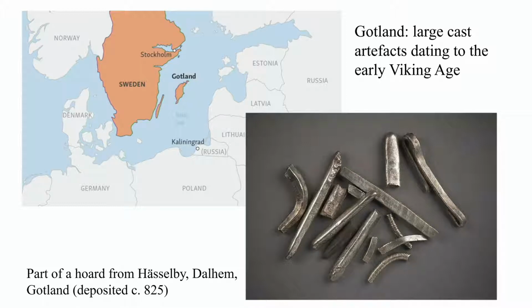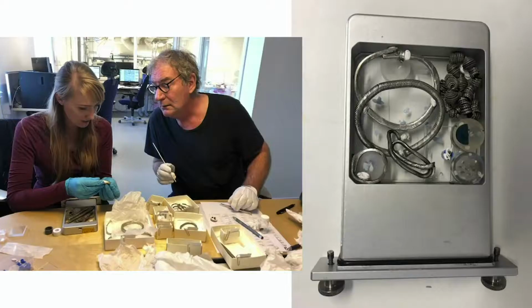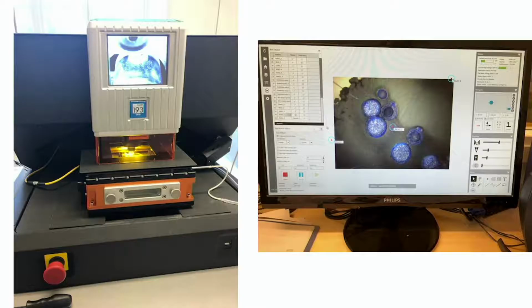And here is an example of a hoard that we also looked at. Here it had some coins with it, but most of the silver is, as you see, as rings, as ingots, so not coins. So we analyzed some of these hoards from Gotland, which we know come from the 9th century. And so here is Melanie Schmidt and Gunnar Andersson, who were in Stockholm here. And we analyzed these with in situ laser ablation. We did both trace element analysis and lead isotope analysis using this method. Here's laser, here's analysis of a standard, so that's why we make so many holes right next to each other. We don't do that on artifacts.